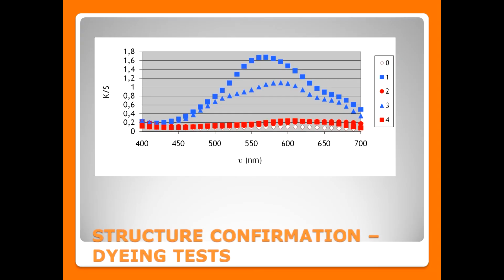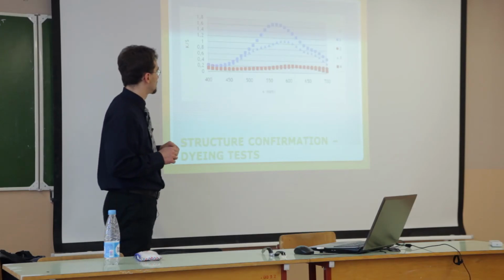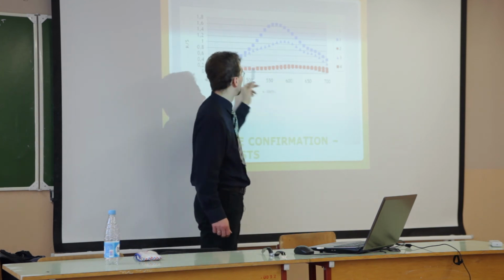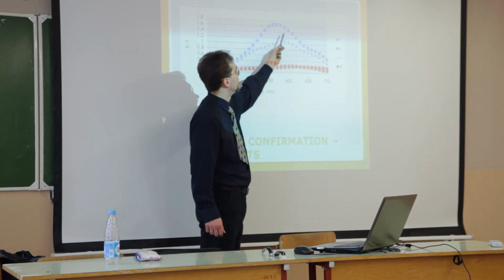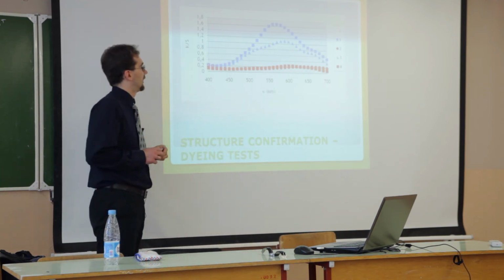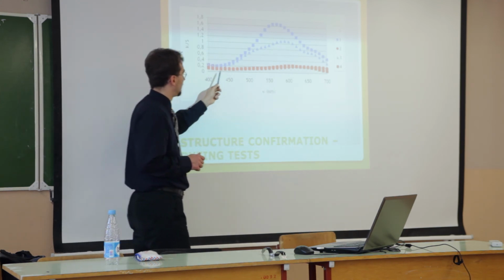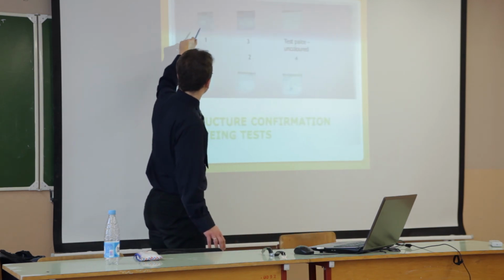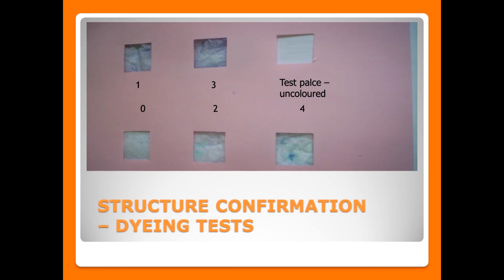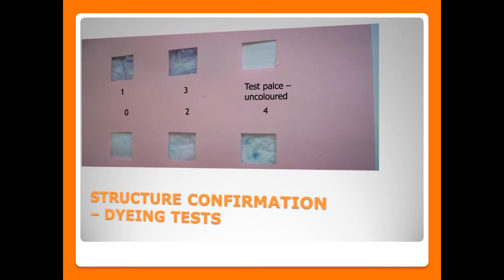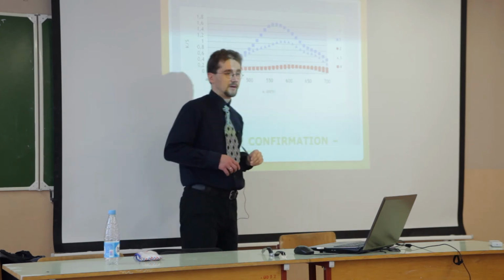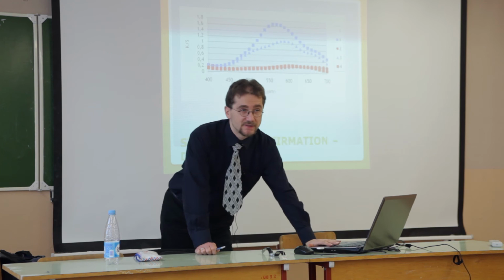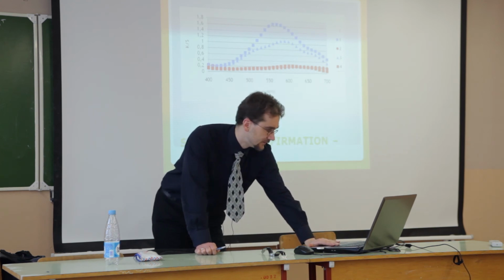We can calculate the Kubelka-Munk relationship, and you can see that white is unmodified, blue are samples with the external acidic layer, and red are those with the external amine layer. So this is in comparison: 1 and 3 acidic, 0 unmodified, 2 and 4 with amine layer, and the area under acidic is much bigger than the area under amine, under samples with the last amine layer.